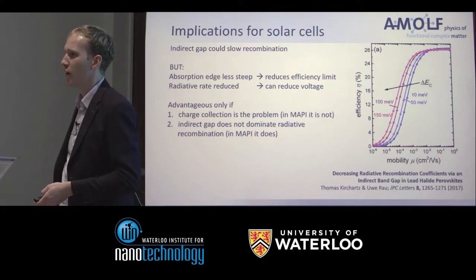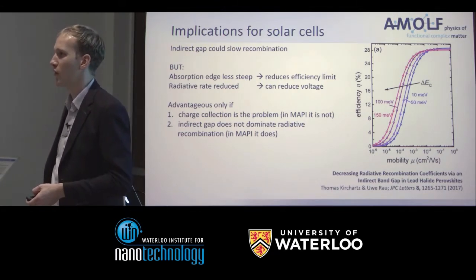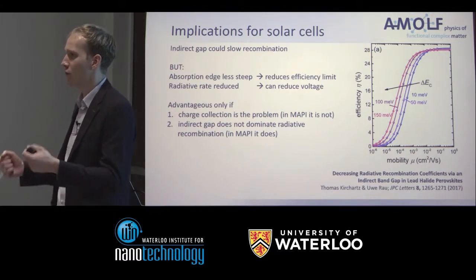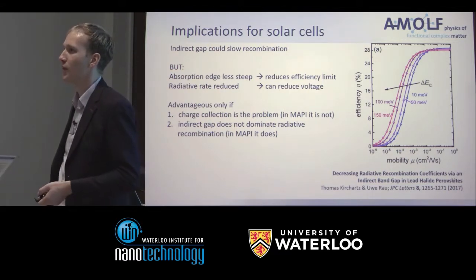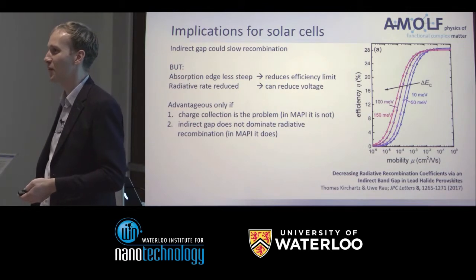And they're still slightly too high in band gap. So 1.3 is on the edge, but you actually want something like 1.1, 1.2 at the maximum. In principle, that would be really nice because they're direct band gap, so they absorb light very strongly, so the whole first transfer is much more efficient. So yeah, I'm looking forward to more efficient 1.1 eV perovskites that are also stable, then we would certainly do this.